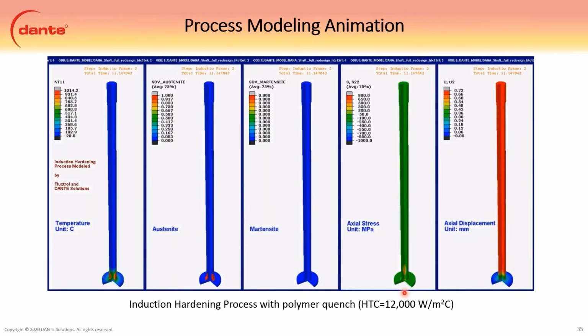So this is an animation, left to right. We have temperature, austenite, martensite, axial stress, and axial displacement. You can see our austenite formation as the inductor moves up, our martensite formation as the spray follows, and you can see this interesting tensile spike that runs up ahead of the inductor. You also have high tension in the core, which balances the compression from the martensite transformation. But this tensile spike that runs out ahead of the inductor is the reason you can crack the end of the shaft if you don't shut the inductor off. I'll let this run through so everybody can take it in; I know it's a lot, being five figures.